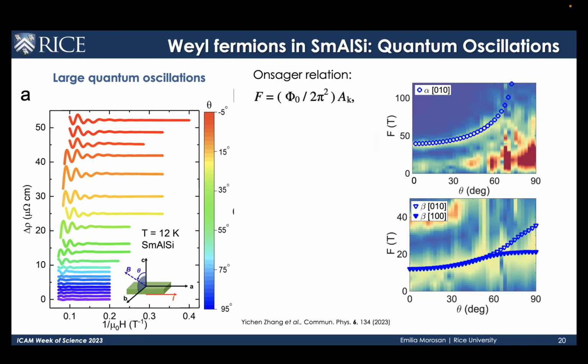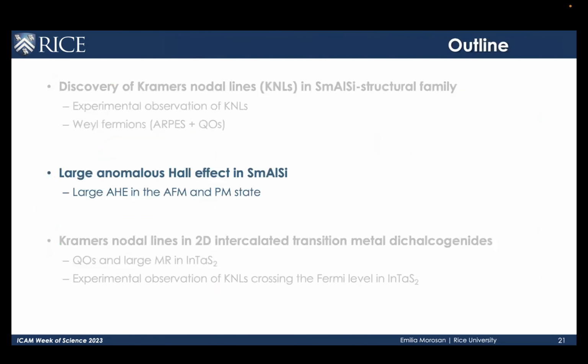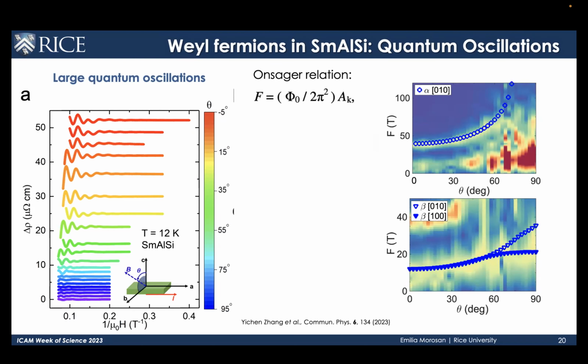So altogether, with ARPES and quantum oscillations and DFT, we were able to paint a picture where the experiment and theory agreed of these Kramers nodal lines, which then turn into Kramers-Weyl fermions when we break time reversal symmetry. And maybe I haven't told you anything about the breaking of time reversal.